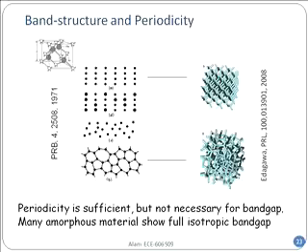If you didn't have a band gap, you couldn't look out of the window. The reason is that the window is made of silicon dioxide, a form of glass. It's an amorphous material, of course, because it was randomly processed. Light still shines through. That means there must be a band gap, otherwise how does the light come through? Now if there is a band gap in an amorphous material, then surely band gap is not a property of silicon alone. So this is a very important point that you should not miss.